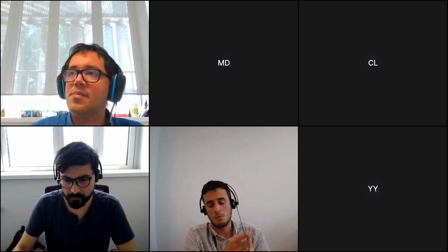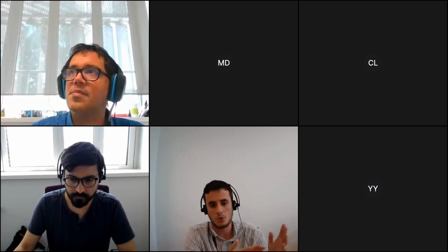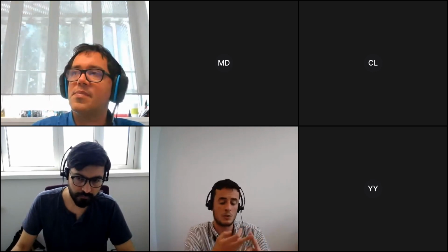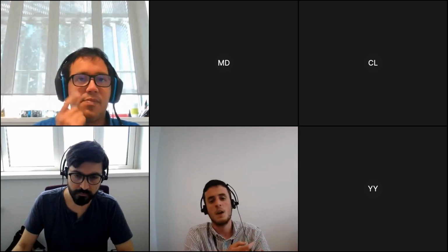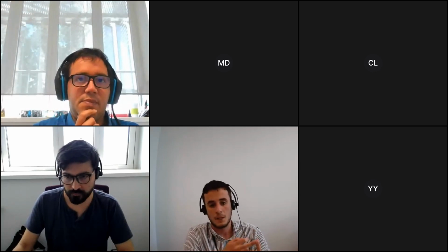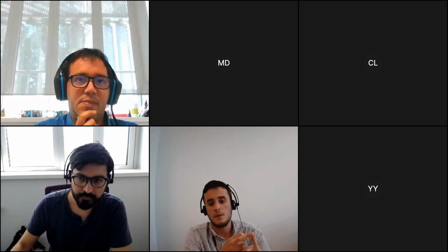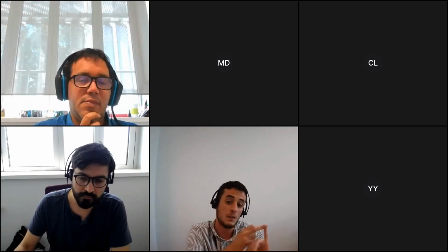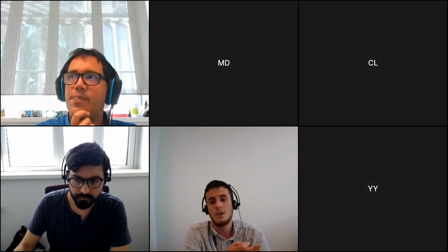At least the model that I described on Monday takes the pressure for the electrolyte inlet, but it also takes the densities, the viscosities, and the contact angles. So the chemistry of the active material can be taken into account through the contact angle, because of course different chemistries will interact differently with different electrolytes, and these contact angles can be taken into account.